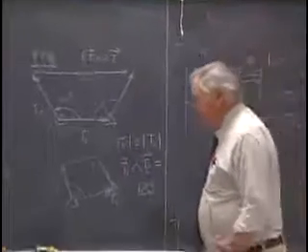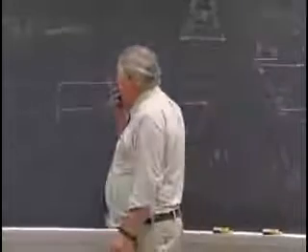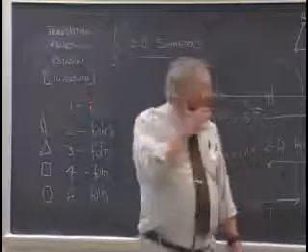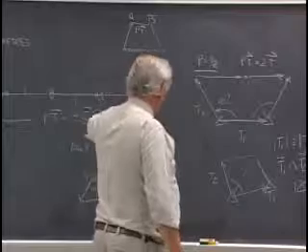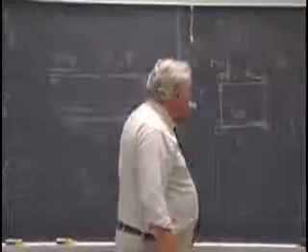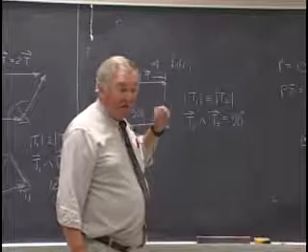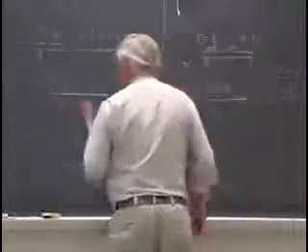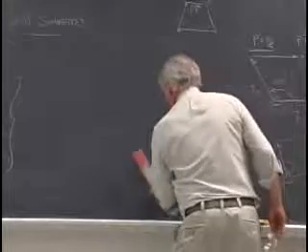So, with this simple-minded little construction, we've found two profound things. That there are 5 kinds of rotation axes, including the one-fold, no rotational symmetry at all. And it turns out that there are one, the general lattice, the hexagonal lattice, and the square lattice. There are 3 kinds of two-dimensional lattices that are required by these symmetry elements. So these require that there be 3 lattices of different specializations that are able to accommodate them.